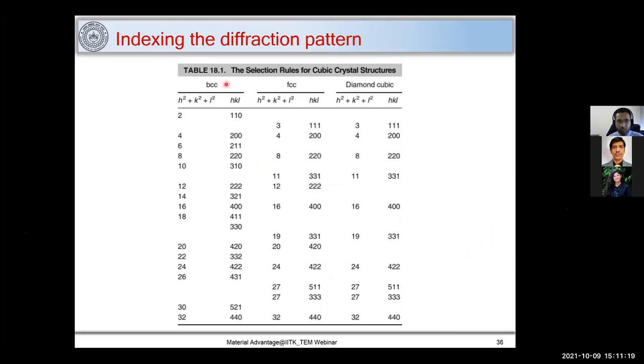So we have BCC, FCC, and diamond cubic, for which we have a set of rules. We call them extinction rules, so you can read about extinction rules. Not all planes will diffract from these crystal structures. In the case of BCC, you have h square plus k square plus l square as 2, 4, 6, 8, 10. So here h plus k plus l is equal to even. Only then does diffraction occur.